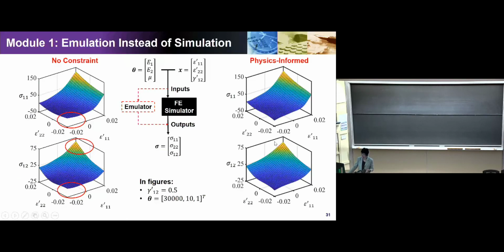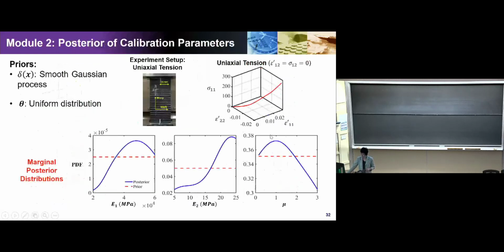The first step is to build the constitutive relationship using the computer model simulation. The stress sigma is a function of theta as well as the input x. In this process, we also used some physics-based knowledge to put constraints on how the stress and strain may change at the corner, which is very nonlinear behavior. If you do not put constraints, that's what you get, but the physics-informed one gives you a more accurate prediction.